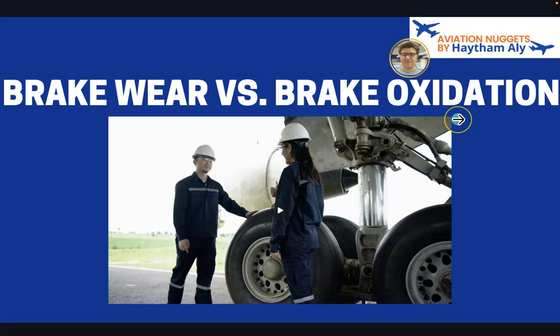It is another phenomenon that may harm the brake unit. And as a pilot or maintenance personnel, if you find a brake heavily oxidized, you need to change the brake unit as fast as you can. Because if the brake is heavily oxidized, it can easily fracture or rupture, and the aircraft can suffer from brake fire, hydraulic leakage and an uncontained failure of the brake unit.